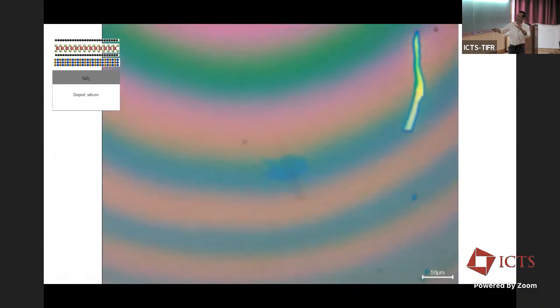All right. So here is a way I can show you how to make such a device. For example, I want to make this 4-layer structure: graphene, TMDC, that is molybdenum disulfide, another layer of graphene, and boron nitride at the end. You take out the graphene first, then we identify a layer of TMDC. You can turn it around, and when you're happy with the orientation, you essentially pick the whole thing up now. So these two will come up, a layer of graphene and a TMDC layer, or the molybdenum disulfide layer.